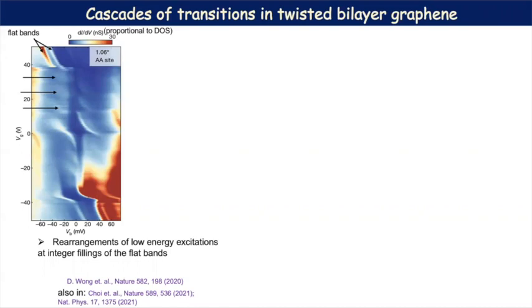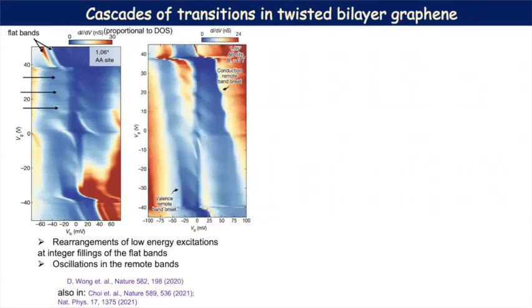Now, something unusual happens when the chemical potential just goes inside this flat band, and you can see that instead of these 2 peaks, which should shift with respect to doping, in this manner, we have this rearrangement of low energy excitations in the form of a cascade. And this one they measured on the AA stacking region of the twisted bilayer. And when they looked into the map for the AB stacked region, they found something like this, where you can see these oscillations in the onset of the remote band.